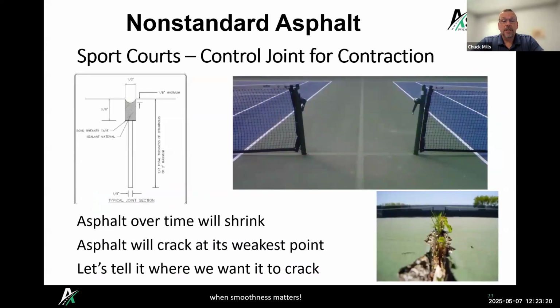So, one of the big problems is we're paving a big area in most of these courts. And we're not going to see cracking from traffic. We're going to see cracking from the asphalt shrinking over time. And where's that asphalt going to crack? It's going to crack at its weakest point. So it might be on a paving seam, things like that.